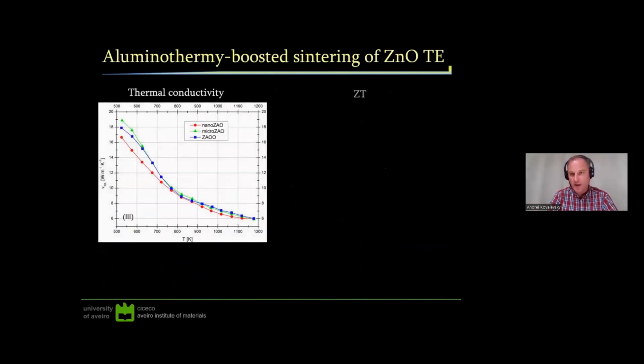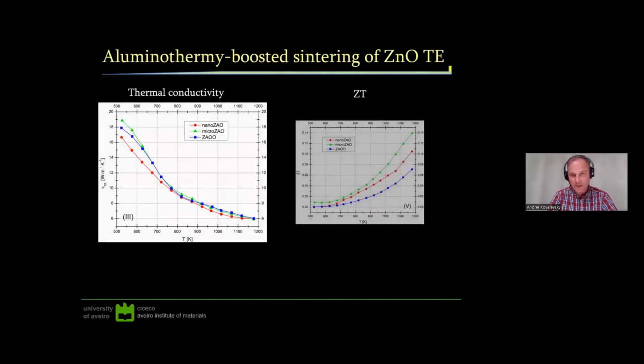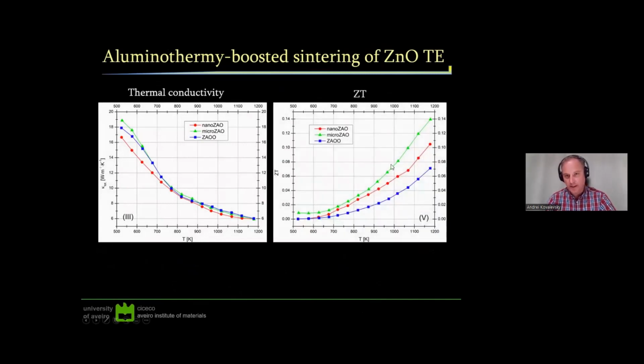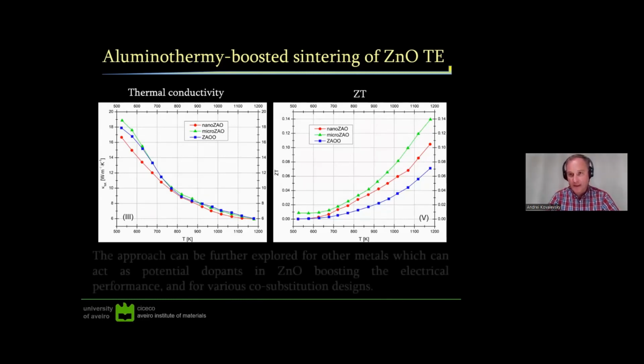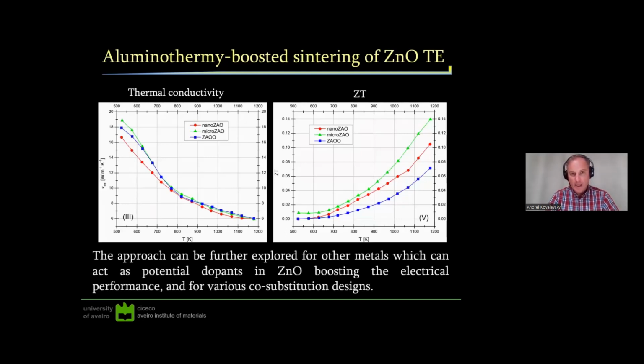Finally, if we speak about ZT values for these materials, you can see that the materials prepared using metallic precursors have much better performance compared to the base materials. And of course there are many ways how we can play with the precursor and the microstructure of oxides to advance their thermoelectric performance.